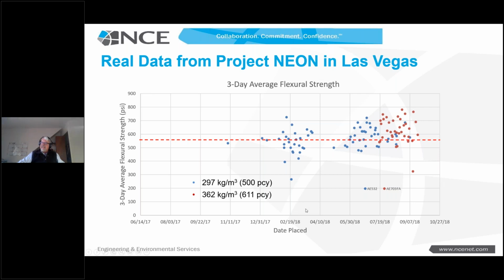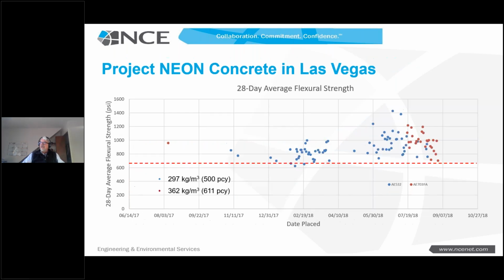Even in Vegas, this is a cool time of year, but by the time we get to the summer and things really start warming up, it's almost the same. Maybe you could argue at 3 days, a little bit more strength with the higher, but by the time we get out to 28 days, one, astronomically high flexural strengths, and two, almost no difference. As a matter of fact, statistically, no difference in strength between 500 pounds total cementitious and 611. These both have 20% Class F ash, same water cement ratio.